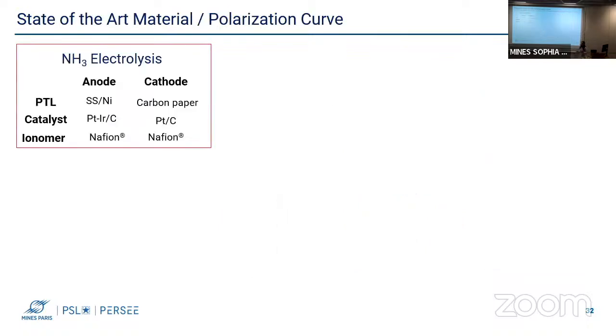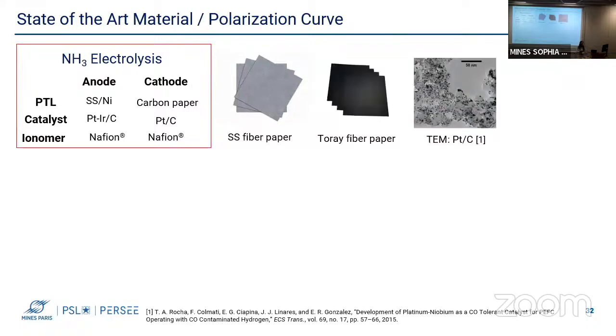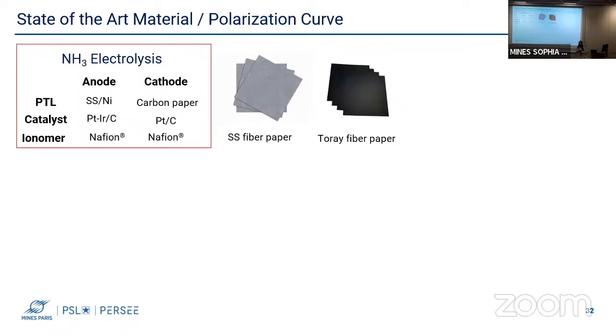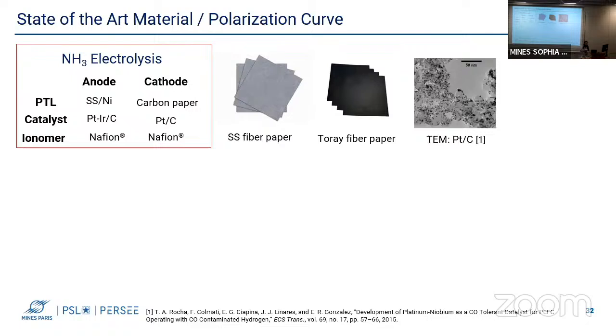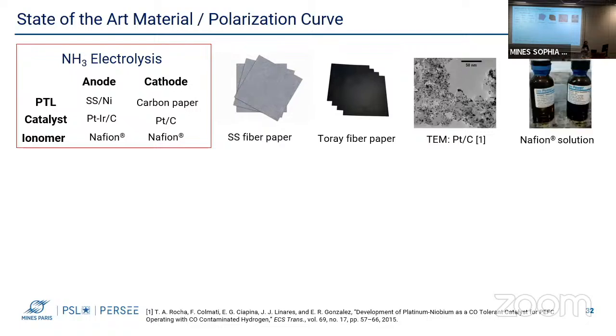The state-of-the-art materials for ammonia electrolysis in AEM conditions include stainless steel fiber paper as an anode PTL and carbon fiber paper as a cathode PTL, platinum iridium on carbon as an anode catalyst, and platinum on carbon as a cathode catalyst. As for the ionomer, Nafion has been most commonly used, as well as polytetrafluoroethylene as a binder, with no study reported on the use of an alkaline exchange ionomer.